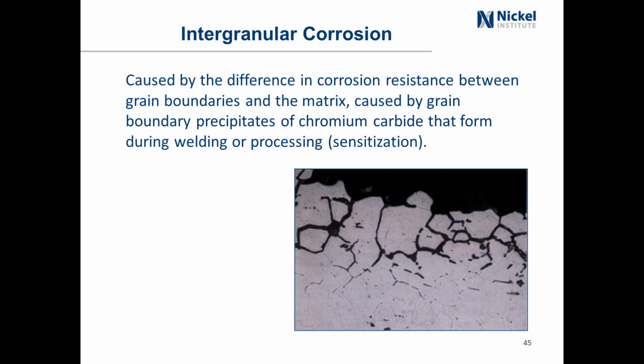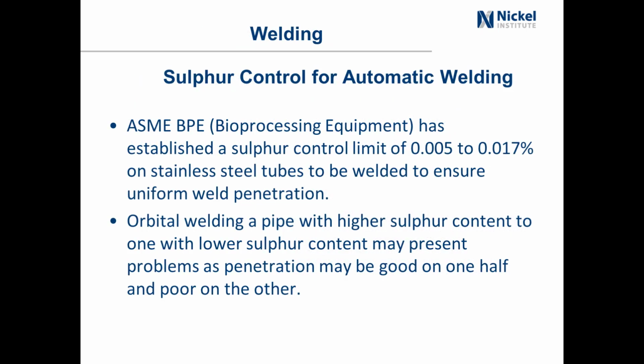And one final little thing I'm just going to mention here is about sulfur control for automatic welding. In the ASME bioprocessing equipment standard, it has established a sulfur control limit of 0.005 to 0.017 on stainless steel tubes to be welded to ensure uniform weld penetration. This is important when you're doing orbital welding of a pipe, because sulfur is considered a surface active element, and if the sulfur is too low, you don't get proper weld penetration, so you could be orbital welding and you don't get full penetration of your weld.